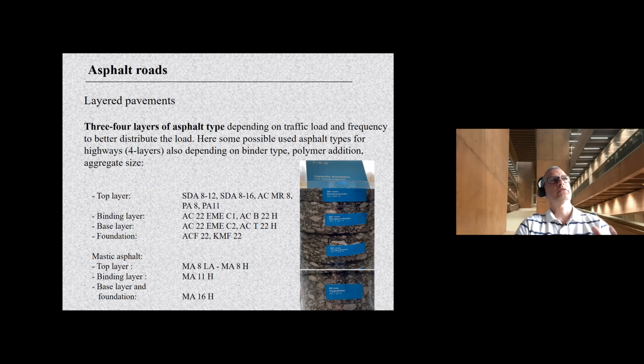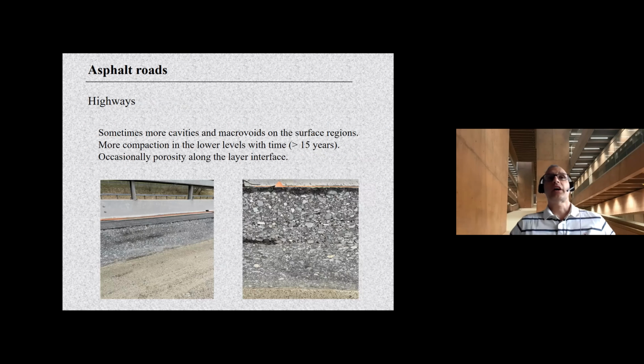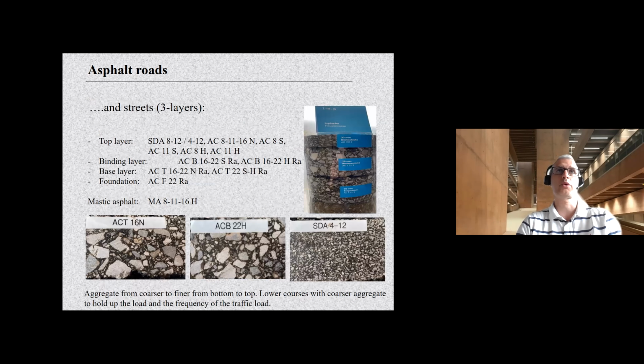Generally, the conventional roadways are composed of 3 layers, and highways are sometimes composed of 4 layers of asphalt material. Here is a highway, a pretty heavily trafficked highway. You can see some more cavities and macro voids on the surface region. It is a 15 years old highway structure, while in the layer underneath, you can see more compaction because of the load of the material, the compression of the material. Although along the interface of some layers, we can also find some porosities and pores.